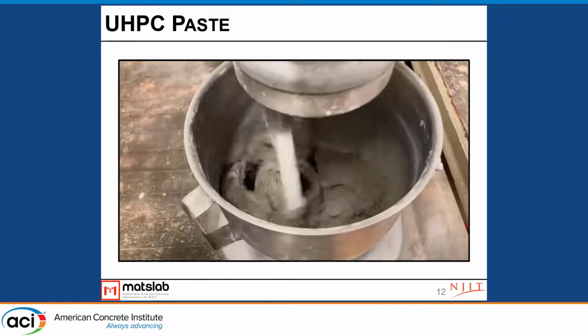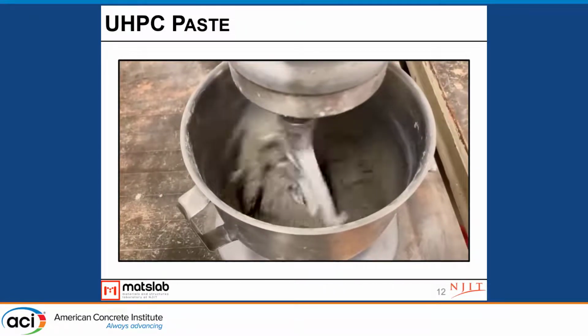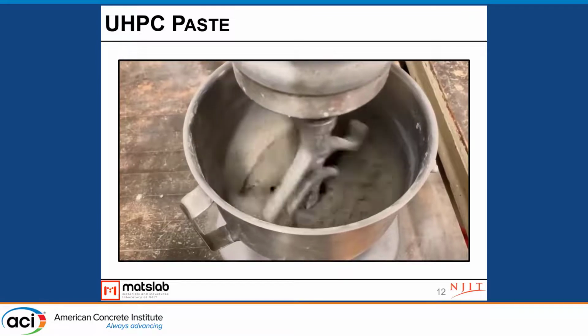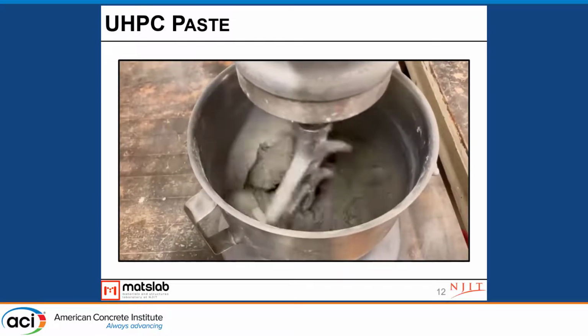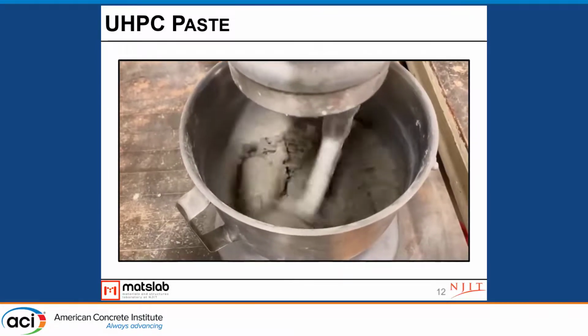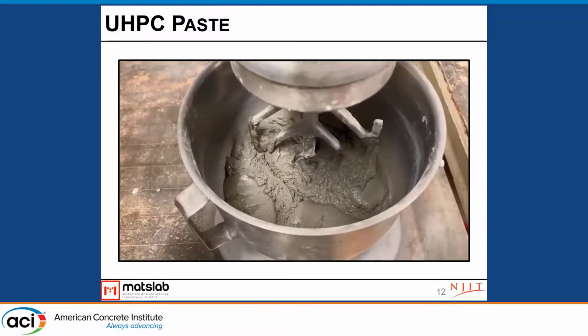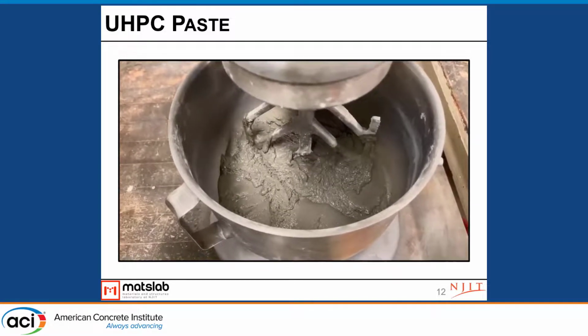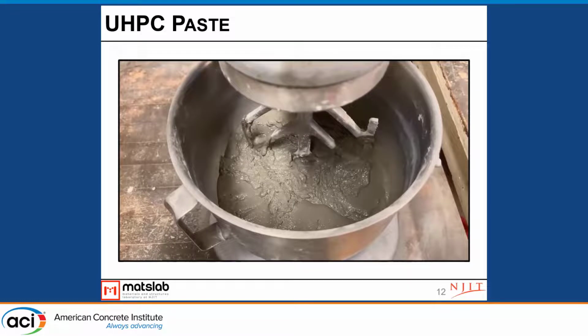And here you can see, a few minutes later, you have this nice paste. At the end of this mixing, I stopped the mixer to see how the viscosity is. This is the stage where you can add the fibers and continue the mixing to disperse the fibers completely.